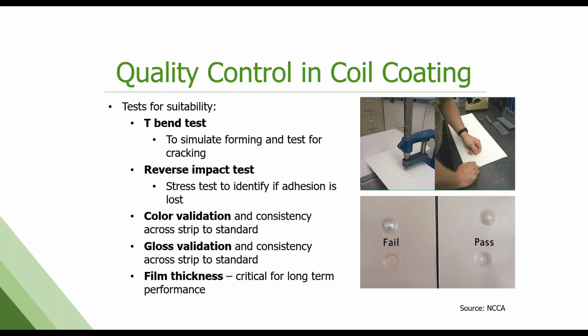So the quality control that we do off the paint lines very much mimics or tries to mimic the forming and fabrication that's going to take place downstream, right? So we do a T-bend, we bend the metal back on itself with the anticipation that there won't be any cracking or fracturing of the paint or the substrate. We do impacting from both sides to test the paint adhesion, how well the metal holds up to that. We do color validation, which is mostly computer controlled numerically. We measure the gloss and the sheen of the strip, and of course we measure film, which is really critical to the warranty performance long term. So we measure that across the width of the strip as well. Next.